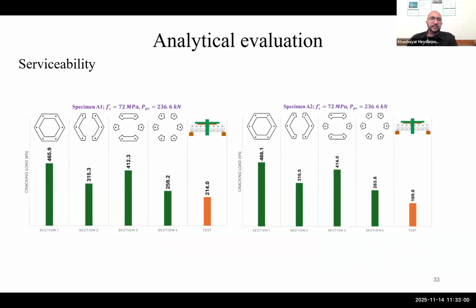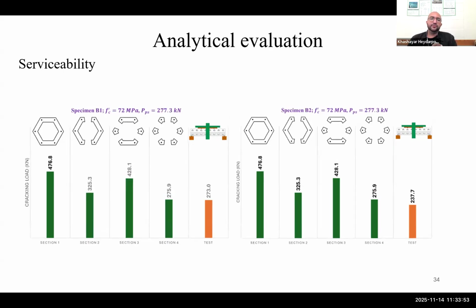And here are also the serviceability analysis results using different cross sections and their comparison with the test result. And as is evident from each of these figures, we can say that the specimen with openings in all legs and also the specimen with openings at the top and bottom legs have had the nearest analytical cracking load capacity compared to the tested specimen, and it corresponds to the loading direction of the test. This one is for specimens A1 and A2. These two, again, the same pattern was observed and the difference was very low for specimens B1 and B2 that had the highest pre-stressing level.